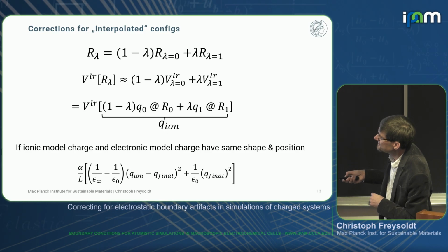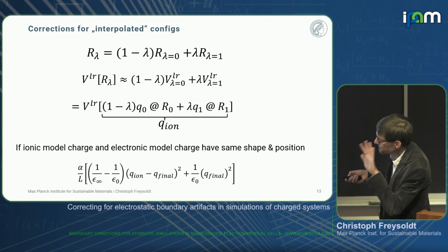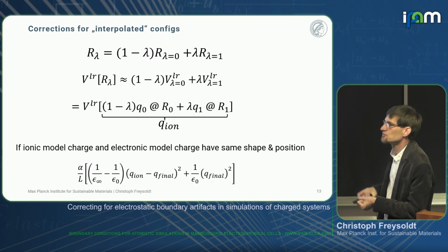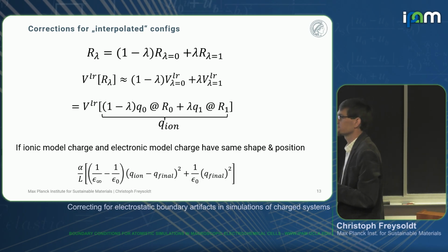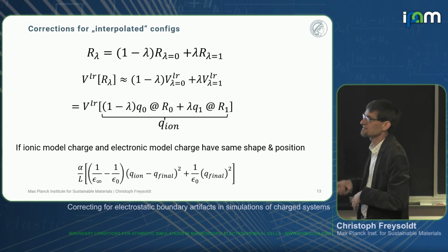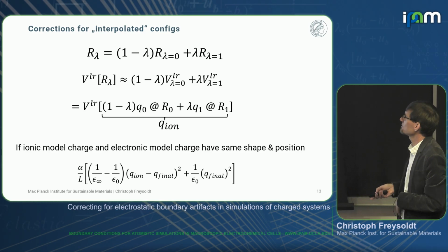And then this is the key point which makes the deviation of those curves, where you see it depends quadratically on the difference between the charge that determines the ionic configuration and the actual total charge that we use for computing the energy. And the prefactor is the difference between the two screening constants. And that is why, if you go away, even at zero charge, where this part here vanishes, you have a deviation in the curve.